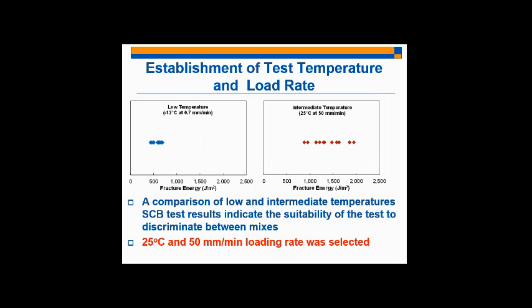And so this slide will better visualize the spread in data between the low temperature testing condition and the 25 degrees testing condition. You can see that at low temperature, at minus 12 degrees Celsius, there's not, again, significant spread, or there's limited spread in the data, whereas at 25 degrees Celsius, 50 millimeters per minute, we see much better spread in our data, which again leads us to pursue this temperature and this loading displacement rate for further development of the index.